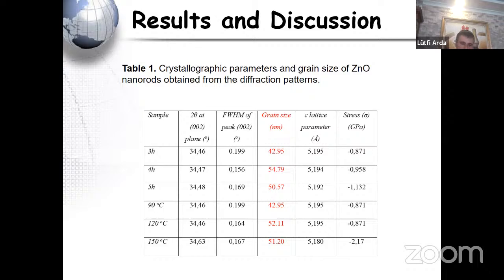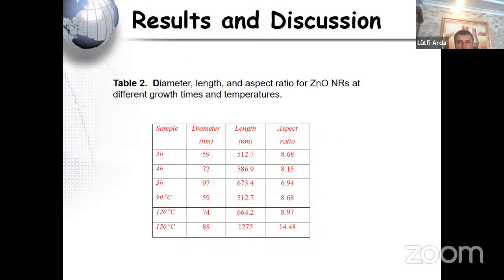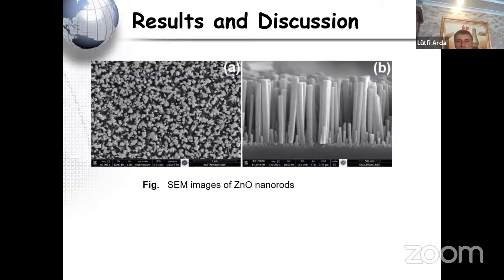After this XRD result, we measured the scanning electron microscope and checked the surface and the cross-section of the nanorods. Look at this figure. On the left side is the surface, a scanning electron microscope top view, and on the right side is the cross-sectional scanning electron microscope, and you can easily see all the nanorods on the zinc oxide thin films.